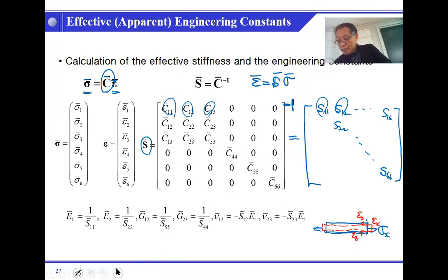So in this case, we are applying stress, sigma xx, and how about this direction? Are we applying any stress? Of course not, but mathematically, we have to think that, yes, we are applying stress, but the stress happens to be 0. So experimentally, we are applying all 6 components of stresses, but it just happens that only one component is non-zero, others are all 0.